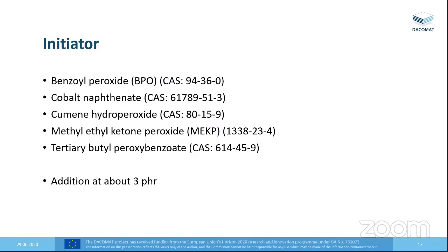So when you make a resin, you have to have a cross-linking reaction, and you have to initiate that cross-linking reaction with these particular thermoset resins. And again, you have a choice of initiators. It could be any of these. It might be a combination of them. But the important thing is that if you look at the bottom of this slide, it says addition about 3 PHR, which is shorthand for parts per 100 resin. So we're looking at maybe a 3% addition, something like that, in terms of weight of the initiator.